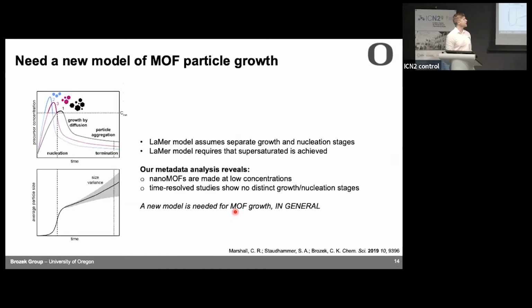or as bulk MOFs. And so when people talk about the mechanism of how nanoparticles grow, they typically talk about the LaMer model. And the LaMer model, which is often used for understanding how metal nanoparticles grow, the idea is that you can track the precursor concentration as a function of time. And at some point, you have so many precursors in your solution that they will spontaneously nucleate to make a particle. The concentration drops, and the particles continue to grow through diffusion-based aggregation.